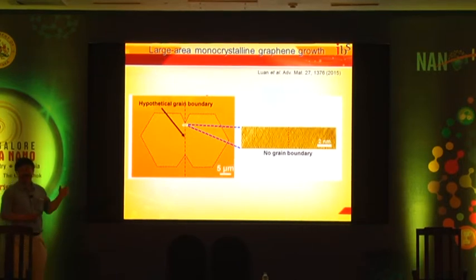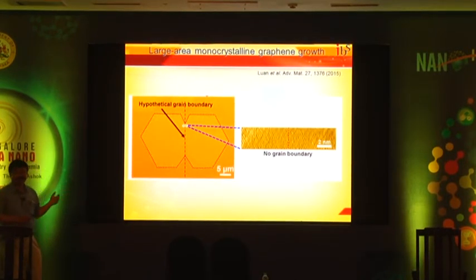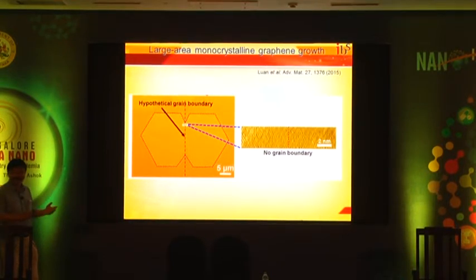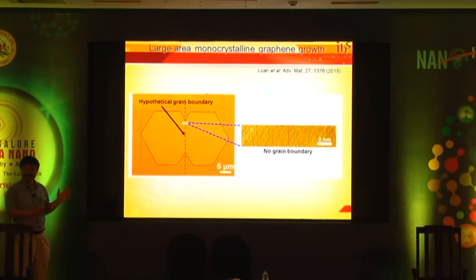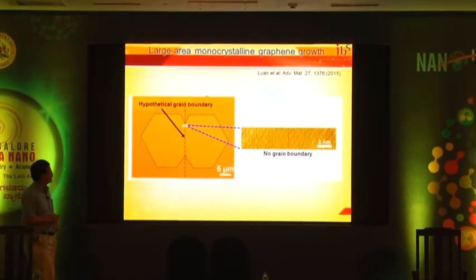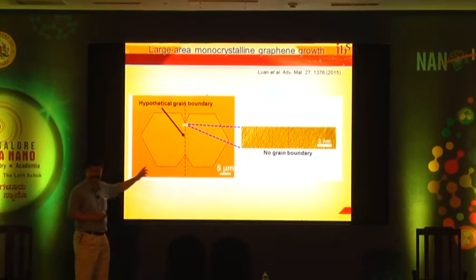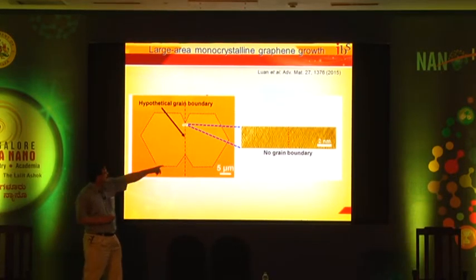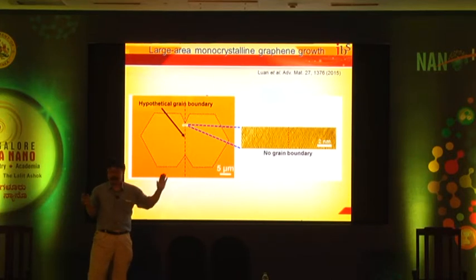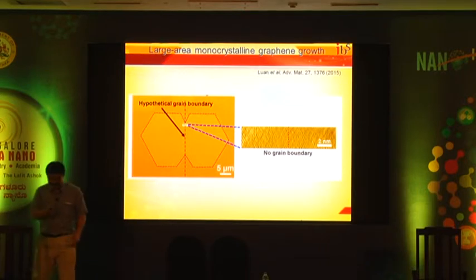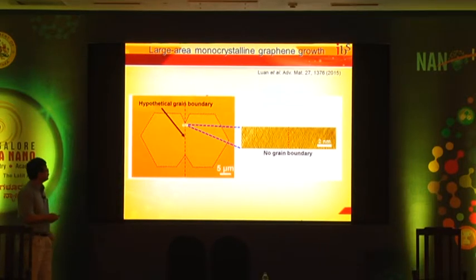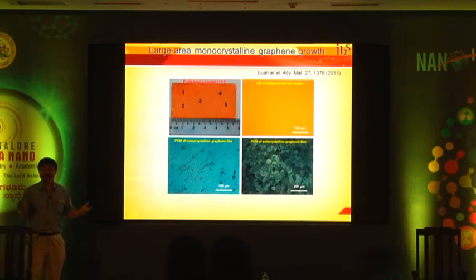Now, when we tried to publish the paper, the reviewers kept arguing, can you really prove there's really no grain boundary at the atomic scale? So we actually did a series of experiments. This is one good example using STM. And you can see on this line, there is no boundary. The crystal structure is well aligned. So we proved it. Now, the question of a large area. Now, this is a centimeter scale.